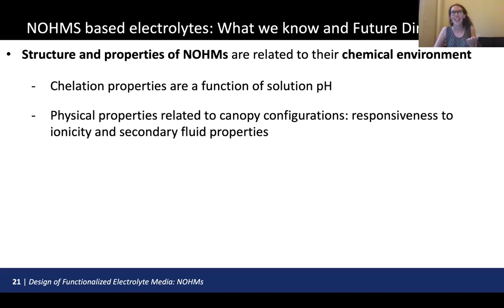Yeah, 100%. That's an important consideration. So again, we saw these NOHMs were effective in chelating copper, but that chelated copper, from what we understand from our results, is not actually accessible electrochemically. So that's why we began to think of ways in which we can release those redox active species. Ideally, we'd be able to have a high concentration of a species in the electrolyte, but then near electrode surfaces release it. So that's why we studied pH as a potential swing. But again, I understand that's not a very practical thing to do.